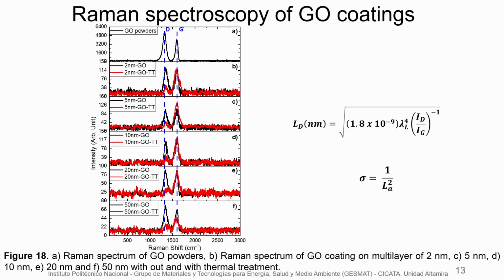We can see that from the powders, very large, very intense D bands. That's why we have a very oxidized graphene material. When we deposit the graphene oxide onto the multi-layer by electrophoretic deposition, we can observe a slight reduction of the D band, and it has been observed that during deposition the graphene oxide is partially reduced. Also, we can see a shift to a higher wave number of the D band, and this is related to a lattice mismatch between the substrates and the graphene layer.